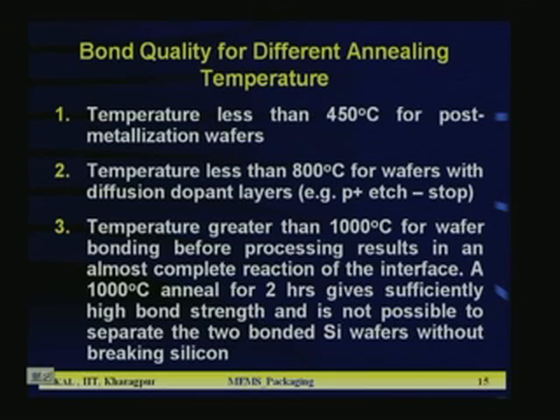The third one is temperature greater than 1000 degrees C for wafer bonding before processing, where there is no P plus layer or diffused layer and no metal line, but it results in an almost complete reaction of the interface. A 1000 degrees C anneal for 2 hours gives sufficiently high bond strength, and it is not possible to separate the two bonded silicon wafers without breaking the silicon. That is one of the unique features of fusion bonding. With 1000 degrees centigrade for 2 hours annealing, the bonding is so rigid you cannot separate it until you break the devices. So, you can use that in a specific application where those limitations I mentioned just now are not there.